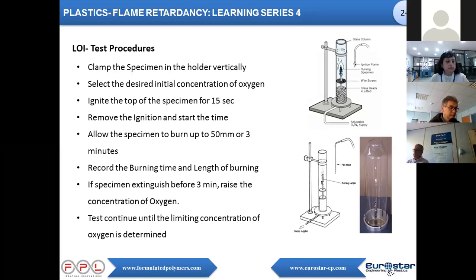Record the rate of burning of the specimen as in the case of horizontal burning. If the specimen does not burn for the required time or length and self-extinguishes, we need to increase the oxygen level in the air mixture and repeat the test with a fresh specimen. The test continues till the LOI value is determined.